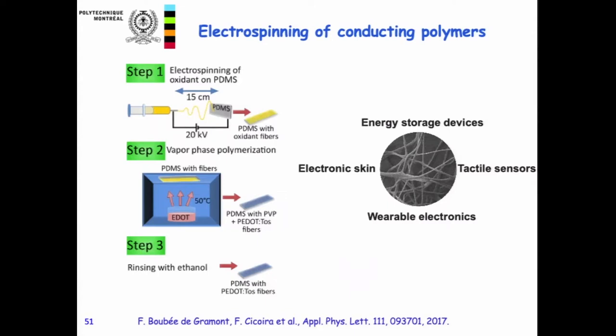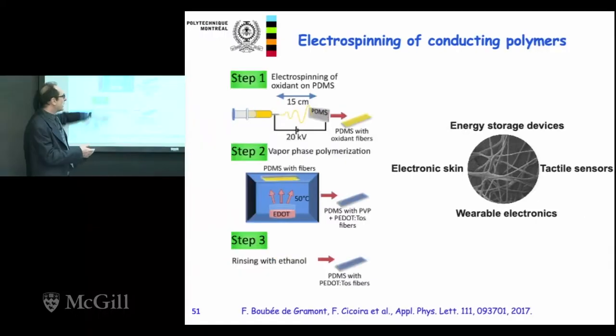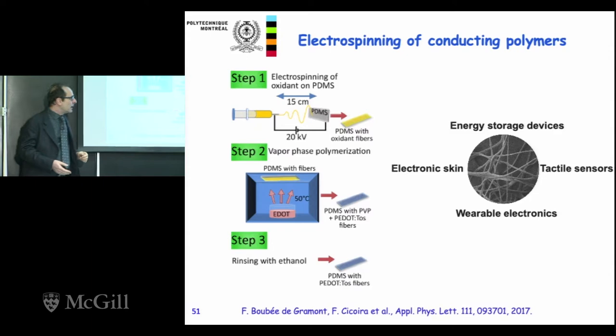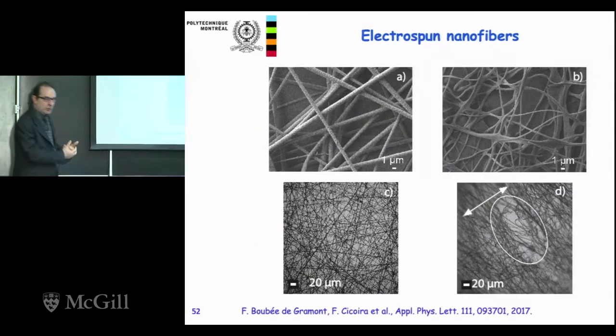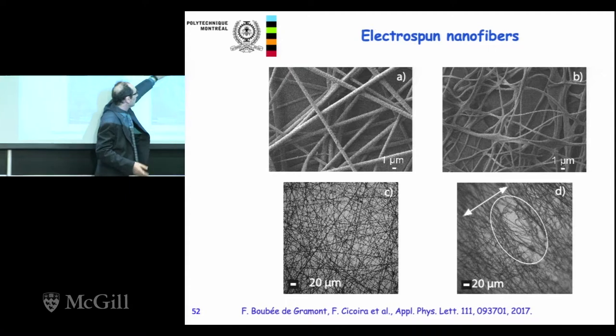I just want to say a few things about another activity we have. So we can also make stretchable electronics based on conductive fibers, which are produced by electrospinning. So the way we make this, first we make fibers of any spinnable polymer, for instance, PVA, polyvinyl alcohol, or polyvinyl pyrrolidone. And then we add to these fibers an oxidant, which is basically iron 3. We expose the fibers to the monomer of EDOT, and in contact with the fiber, the EDOT will polymerize. And finally, we can remove the core of the fiber to get only the shell of the fiber.